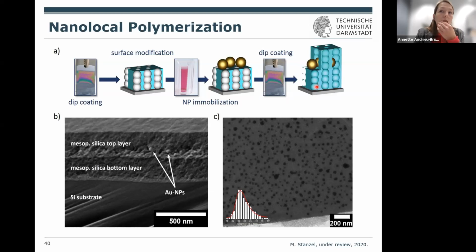Mm-hmm. But do you assume coverage basically of the nanoparticles on your first layer? Do you assume which coverage? Yeah, that's of course the point. Yeah, that's the point with these nanoparticles. So we can control this slightly. You do not want to get too close, at least not in our first study, because if you get too close, of course, then you have this plasmon coupling. This is what you did not want in the first study. Yeah, this is of course the question in this approach. If you want a fully closed layer at that point, how you would achieve that.